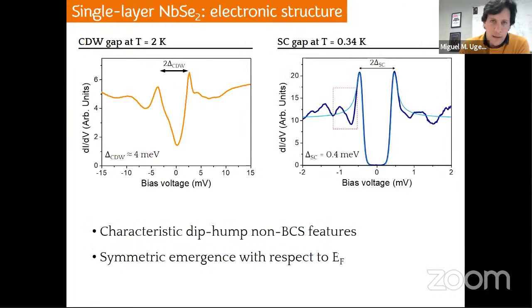If you lower the temperature to 300 millikelvin and go even closer to the Fermi level, what you see instead is a clear development of a gap, which we know corresponds to the superconducting gap. These two are the coherence peaks. And in light blue, you can see the fit to the BCS conductivity density of states. As you can see, the fit is very good up to the coherence peak.